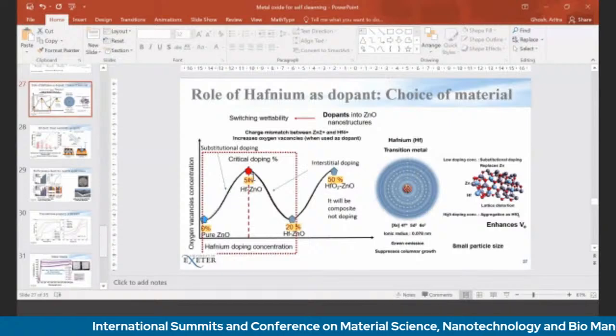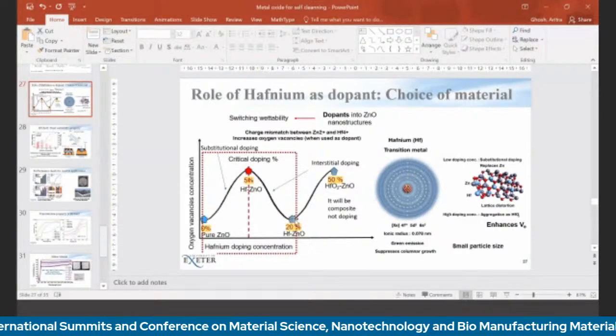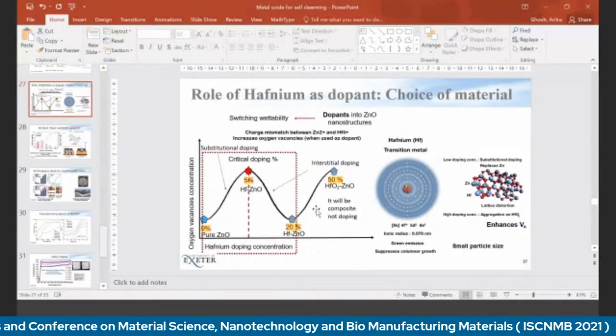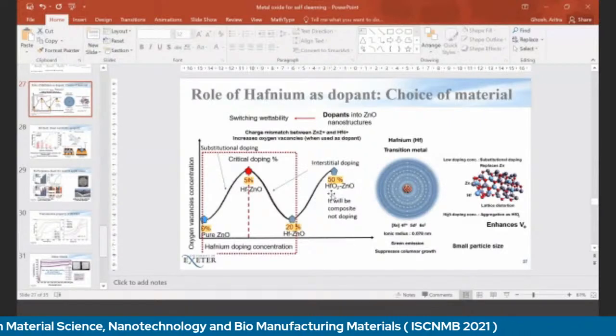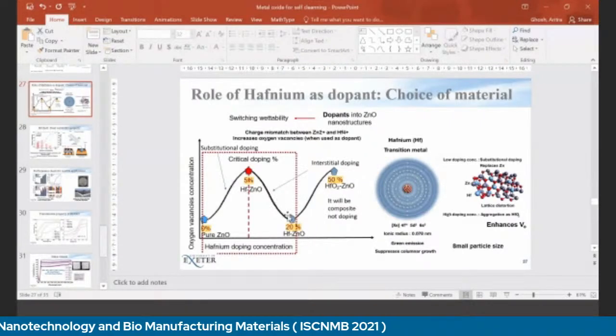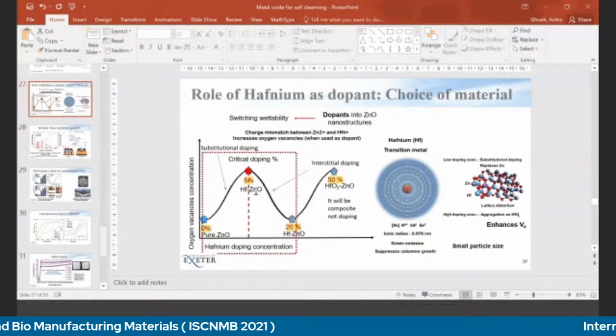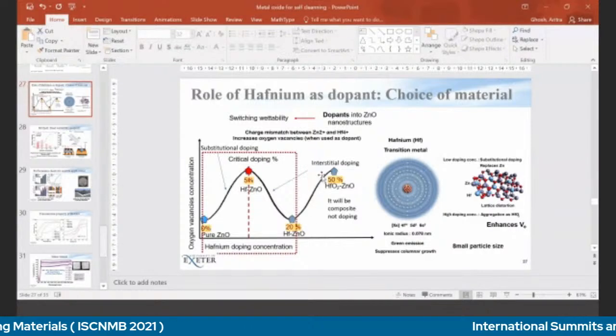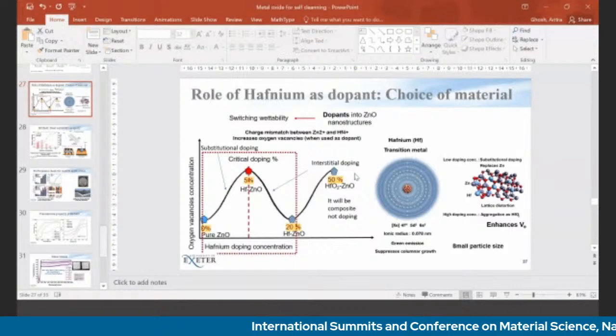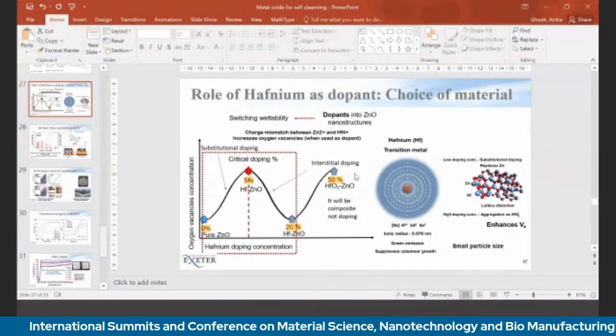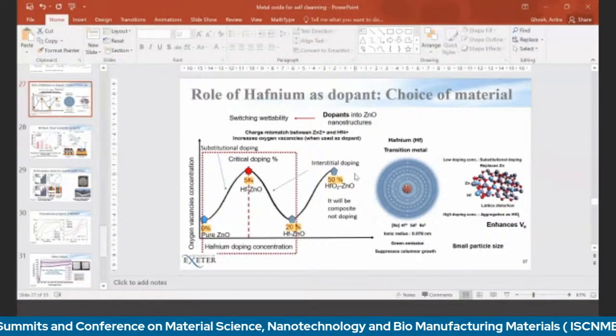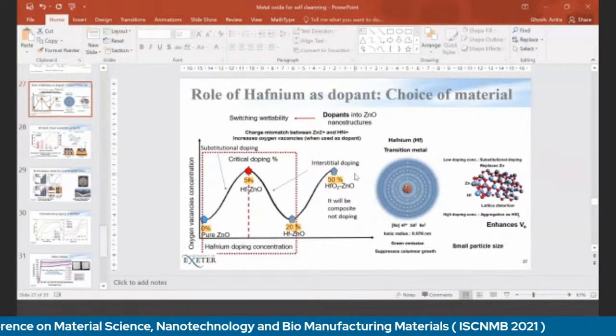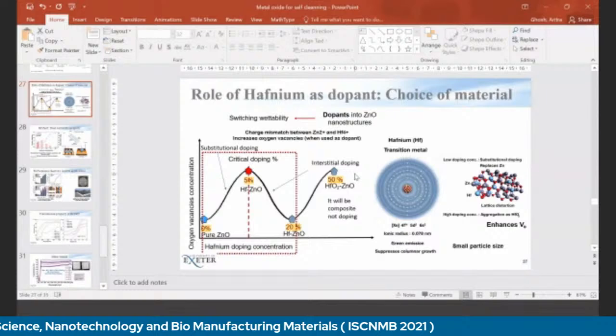And after this 5%, we don't know what happens after 20 to 50%, but we did a little work within this range. We found that when you are doing 5% to 20%, you have interstitial doping. And because of this different phenomenon, you can change the roughness. But yes, you cannot change this switchability after the manufacturing. But during the synthesis process, you can change it. It's not like it is changing under the sunlight or under the UV light.